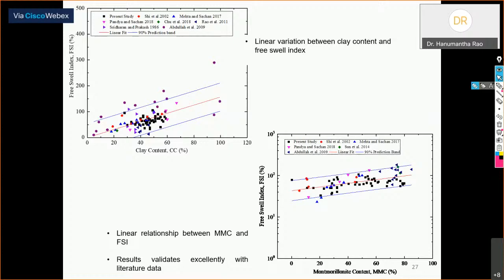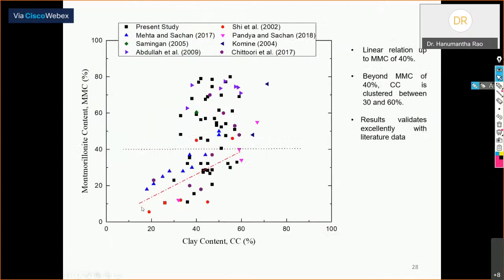So this is the relationship between montmorillonite content versus clay content. When we try to draw the relationship, we found that up to about 40% of montmorillonite, there is an increase in montmorillonite content with increase in clay content, but thereafter it's almost a scatter. It started from about 15%, and then ended up to 70%, because 70% is clay.